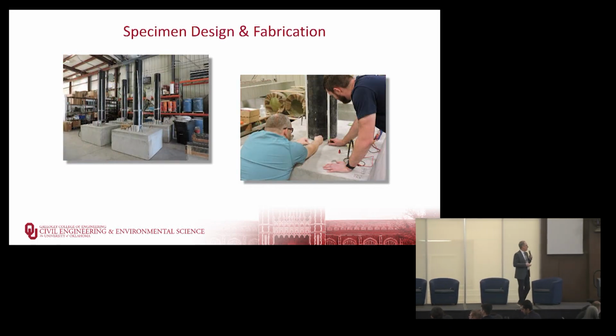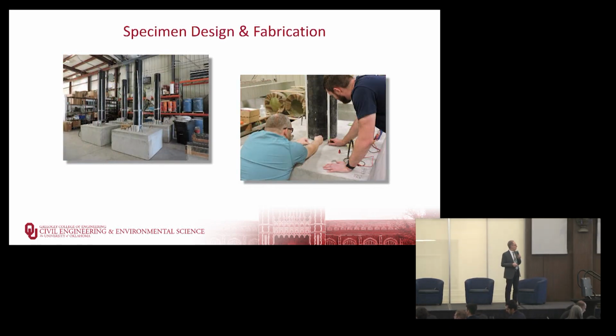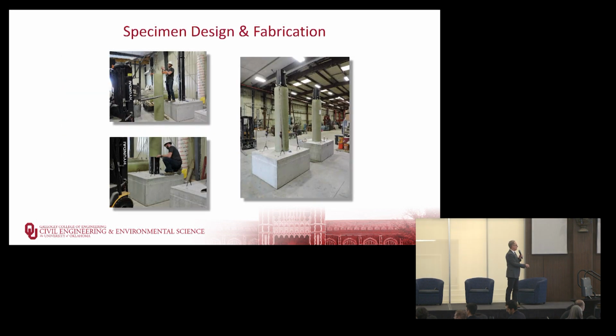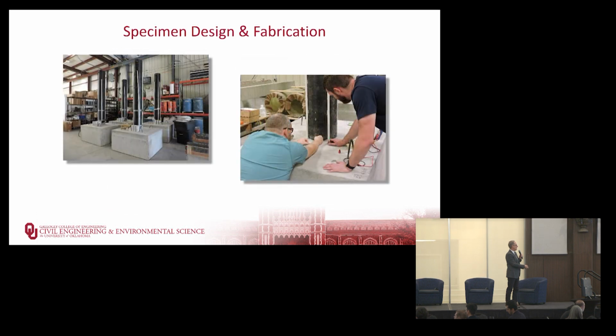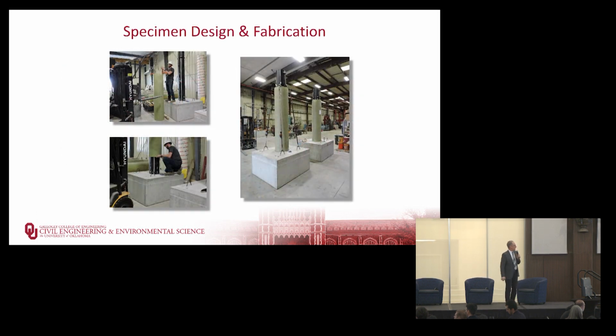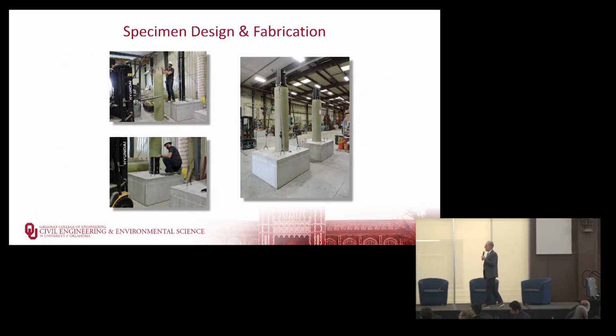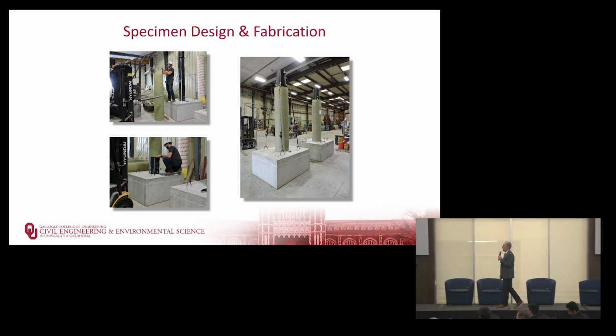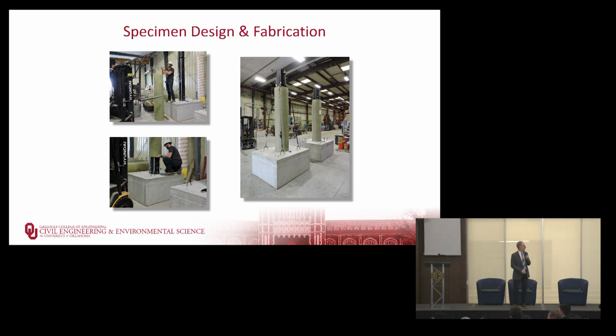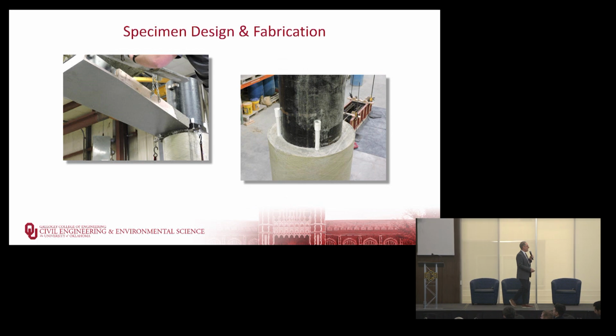remove the formwork, put on some strain gauges on the steel tube, slip the FRP tube over the outside, using spacers to get it in the right place. Put strain gauges on the FRP tube. And then cast the concrete.